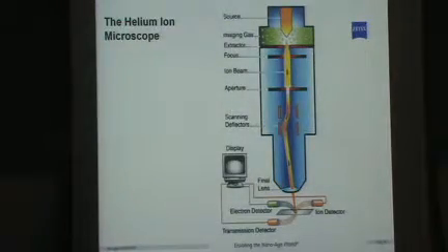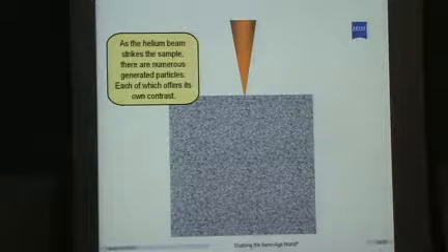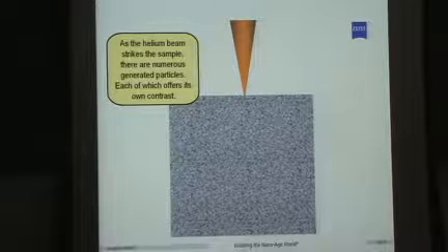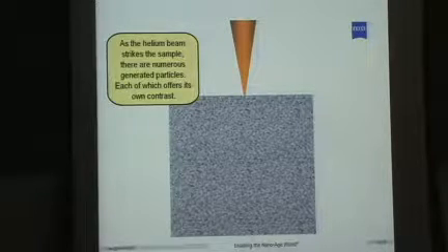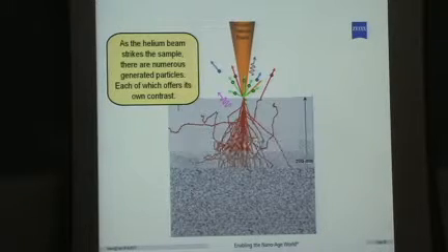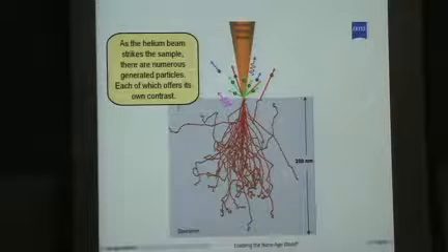So I'm now going to talk about, as that beam enters the sample, the interesting particles that are created. And this was largely explored. There's a lot of people who had studied it as part of the fusion program, because they have, after all, alpha particles, helium atoms, slamming into reactor vessel walls. And they had done a little bit of this research. But no one had really done the research for a focused probe of heliums. It just wasn't available. So if you could reveal and see what's going on under the surface, you see that the helium ion beam can get a couple of 100 nanometers down. And you can see there's a whole collection of particles that are generated here, some right at the surface, some deeper down, and I'm going to talk about them one at a time.